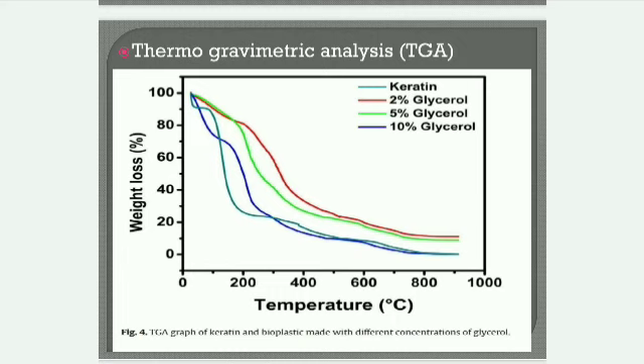Thermogravimetric analysis, TGA. The figure shows the graph of weight percentage from room temperature to 900 degrees centigrade. It is shown that the bioplastic synthesized from keratin with different glycerol concentrations has the same trend of weight loss. The first gradual weight loss below 150 degrees centigrade is due to the evaporation of moisture. The second weight loss between 150 and 250 degrees centigrade is attributed to the plasticizer evaporation, and the final weight loss beyond 250 degrees centigrade is due to the decomposition of quill material.